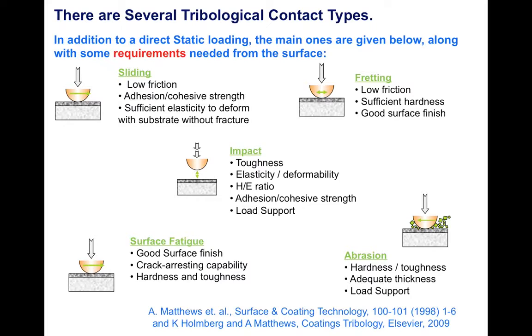And what I've done here is I've tried to identify the requirements of these different contact types. And the first thing to note is it isn't just hardness. You know, some people will believe that all you need is a harder and harder surface and that eliminates wear. That just ain't true by a long stretch of the imagination. In fact, one thing that we often emphasize is the ratio between the hardness and the elastic modulus. If you follow the stuff we write, we often talk about it because it defines something called the elastic strain to yield. So if you have a high ratio of hardness to modulus, it means you can stretch the coating a lot before it yields. And that's more important than hardness, believe me.